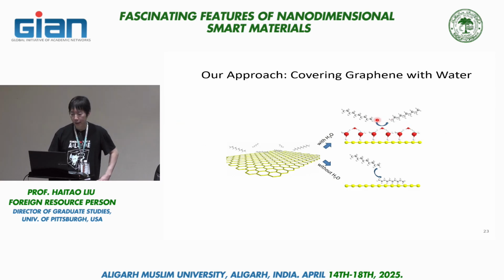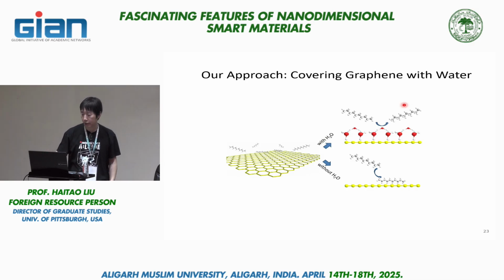And it appears that once you have this monolayer amount of water, the hydrocarbon is less likely to stick to the surface. We think they probably still absorb to the surface, but because a lot of the applications we're interested in, in particular electrochemistry, would involve working in the aqueous environment anyway, it seems that the interaction becomes a little bit easier to release those hydrocarbon contaminants. At least that's the kind of model we're thinking.